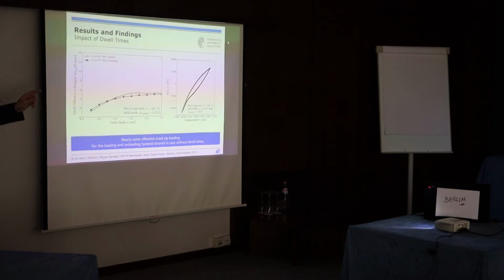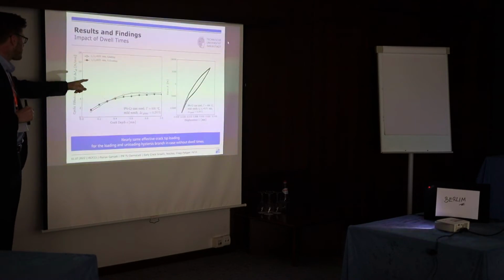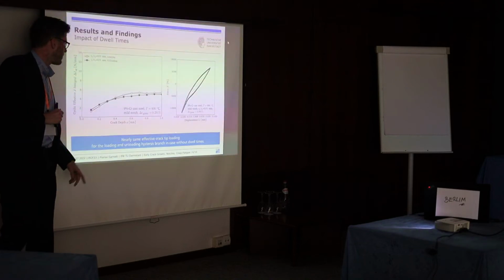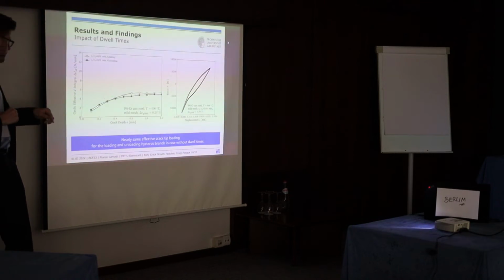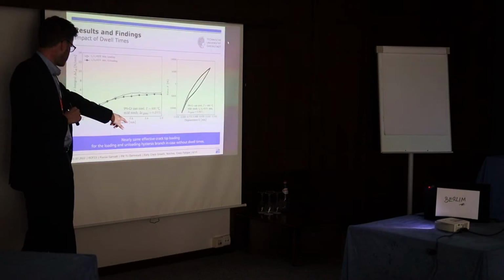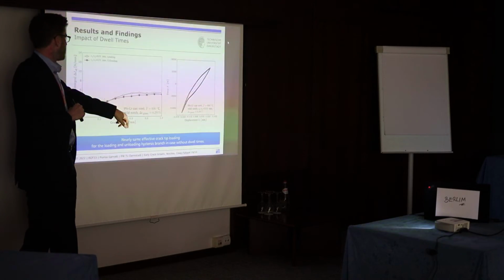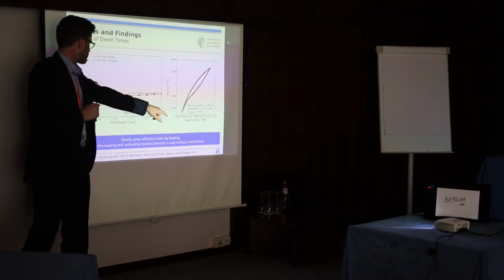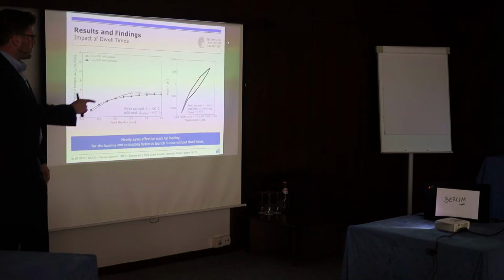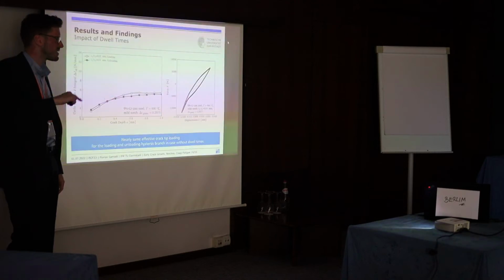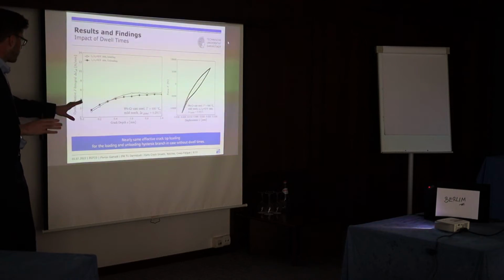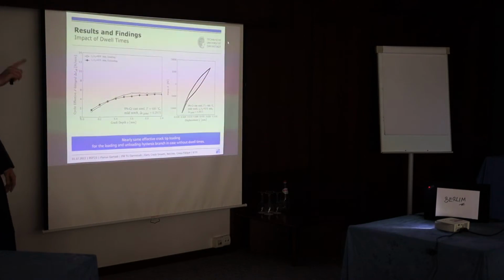Now I would like to focus on one major finding we made here during our investigations, and this was the impact of the dwell times on crack closure. What you see here is the delta J effective value over crack depth for the case without dwell times. So you see that these full and blank symbols here, they belong to the loading and unloading part, and they are almost equal during the cycle. On the right you see a measured hysteresis curve, force displacement curve, where you see kinks indicating crack opening and crack closure.